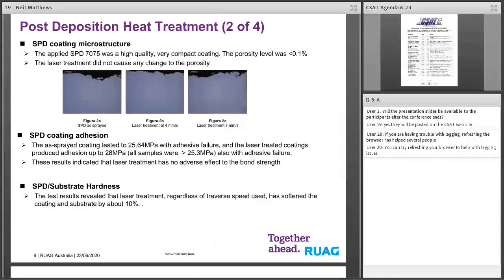So these are the summary of the outcomes: the laser post-heat treatment did not affect the microstructure. There was no improvement or reduction in porosity. It didn't affect the bond strength. We did see a slight reduction in the hardness of both the coating and the substrate. It was about 10%. That is a concern to us with this concept of in situ or localised in situ post-heat treating. Next slide, please.